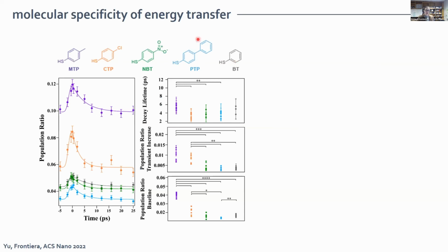There are three key parameters that we can look at in these types of spectra. So for example, we can look at the decay time constant that we see on this picosecond timescale. These range between 3 to about 8 picoseconds, depending on the sample. Ziwei for these measurements made 10 individual batches of colloids deposited onto filter paper to really try and sample the true heterogeneity of these systems. And you can see that reflected in the different points in the error bars over here.